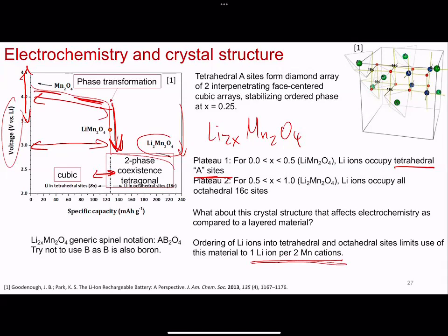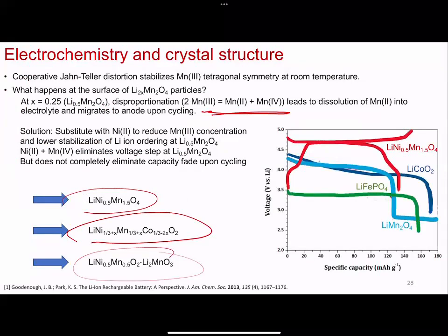So the crystal structure informs us of the electrochemistry, which voltage window we can operate within, and what resulting capacity is going to come out of that. And where we left off is how to then mitigate this challenge that is inherent in the lithium manganese oxide crystal structure and its use as a cathode material. We talked about, well, if manganese dissolution is a problem, but the higher voltage is something that we want to keep, then we can substitute in nickel to reduce the manganese 3+ concentration in the spinel structure. That's great, and it does mitigate that issue somewhat.